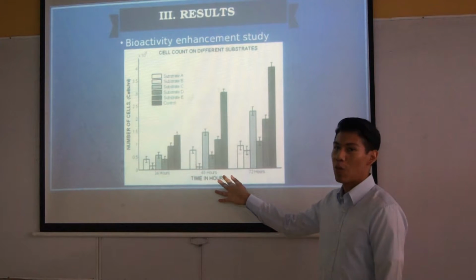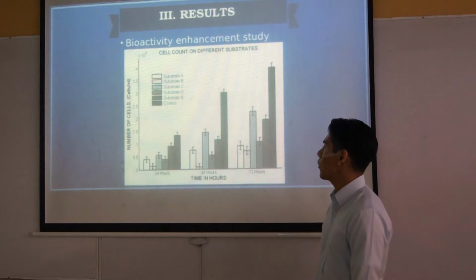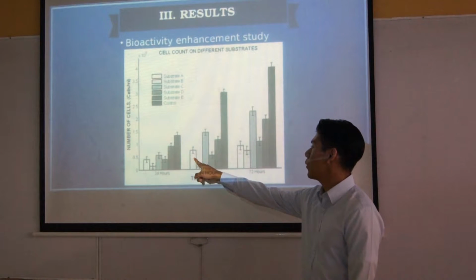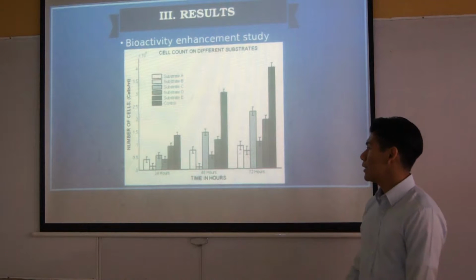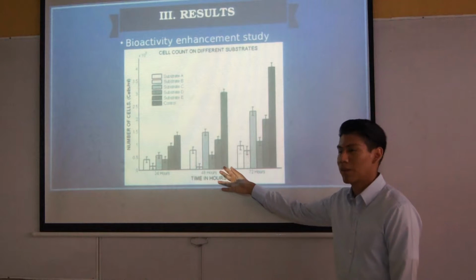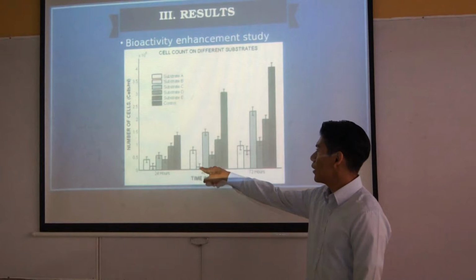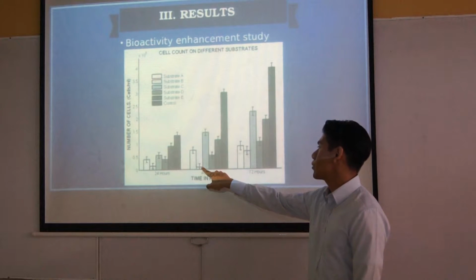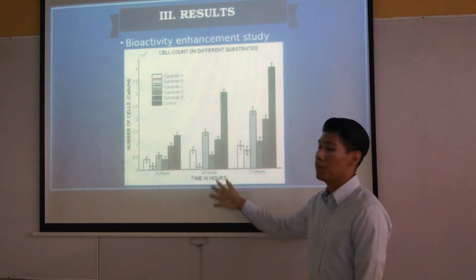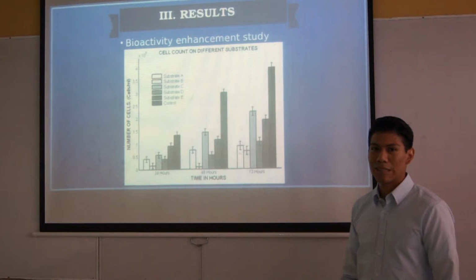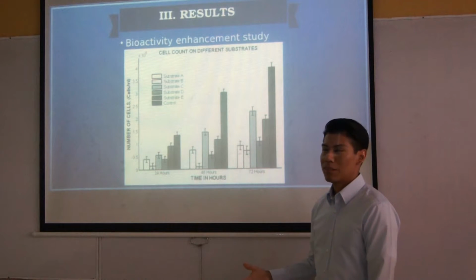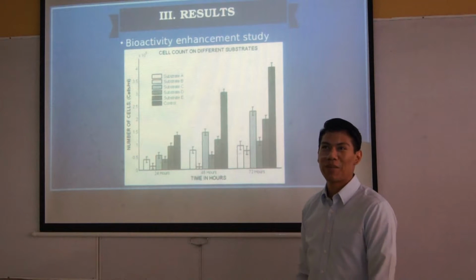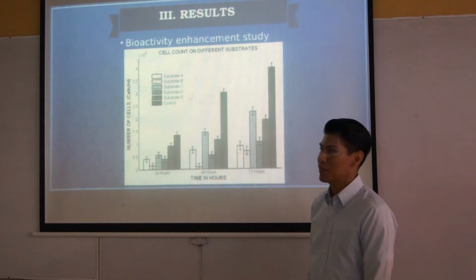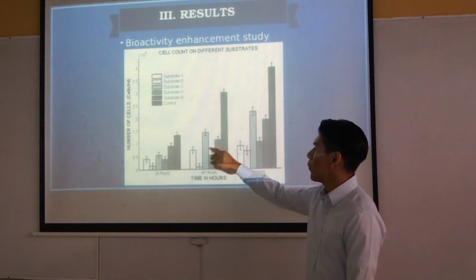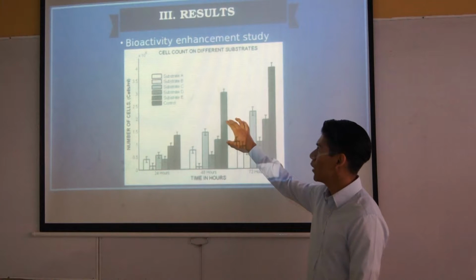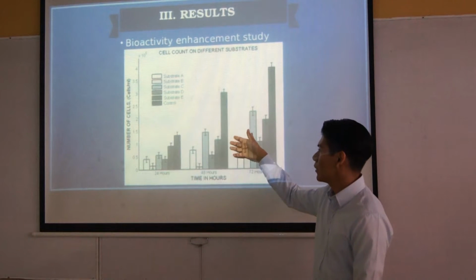Now 24 hours pass, and we have this other cell count. We can see here that only substrate A is not significantly different from substrate D, which is 100% polymethylmethacrylate. Here there are 2 main results. The first result is a negative result in the substrate B, which exhibits cell death and inhibition. In the case of substrates C and E, we observe a very high bioactive behavior and proliferation of cells, mainly because of the cell count. But all of this is always under the constraint of the control substrate in this area.